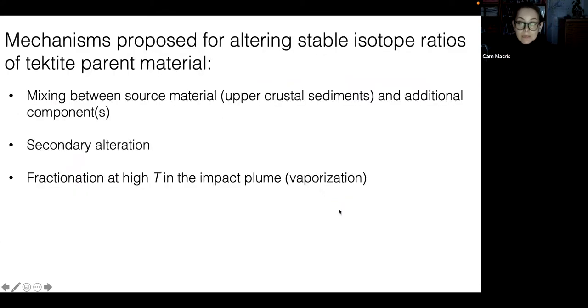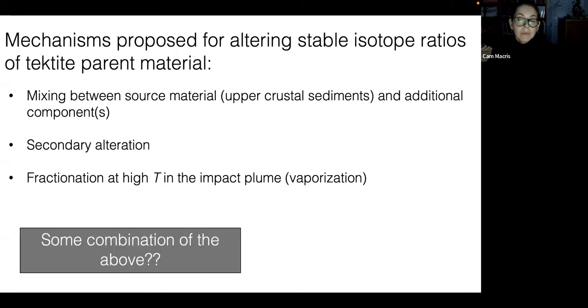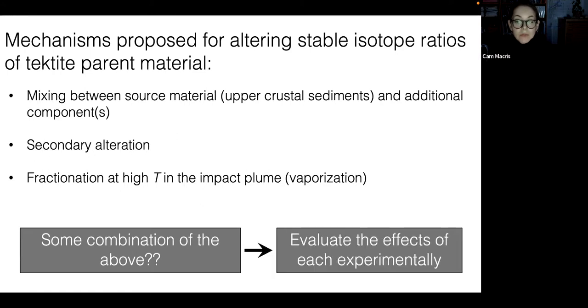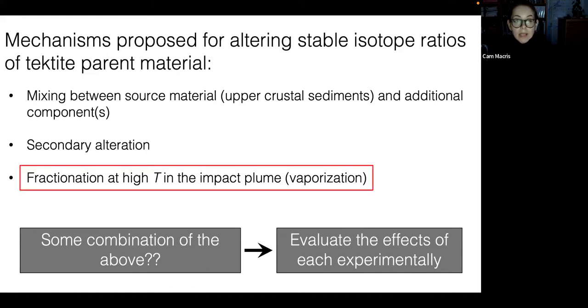Some possible mechanisms that have been proposed for altering stable isotope ratios of tektite parent material include mixing between source material, which we're going to assume are these upper crustal sediments, and some isotopically different component. It's also been suggested that maybe there was secondary alteration. And because we know tektites experience extreme temperatures in the impact plume for seconds to minutes, it seems likely that they could have fractionated due to partial vaporization. In reality, it's probably some combination of the above, and we could quantify the contribution of each experimentally. In my lab, what I can try to tackle is the vaporization aspect.